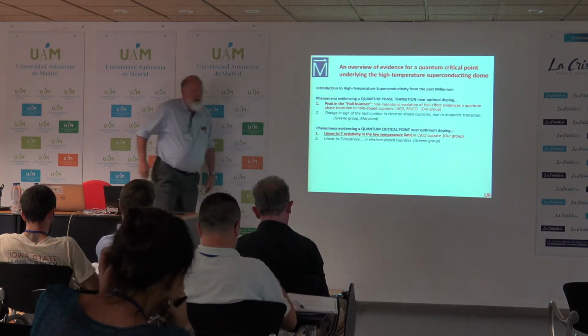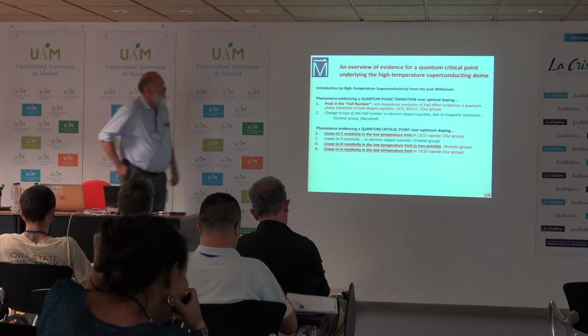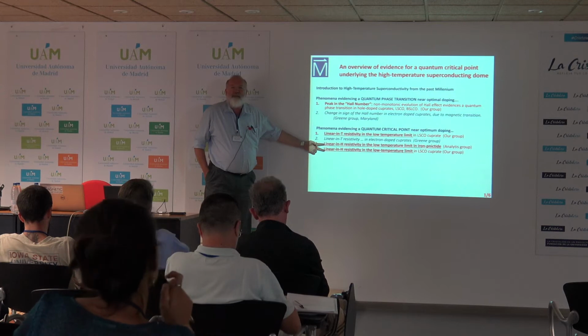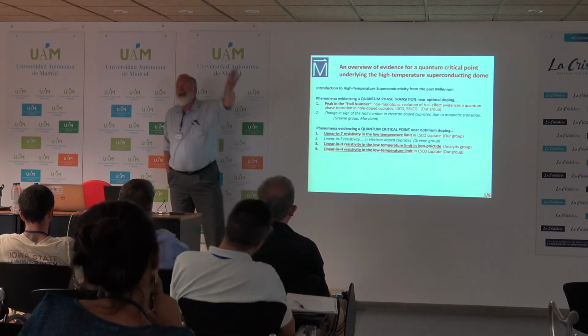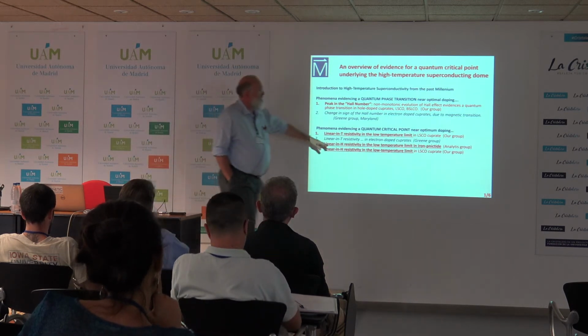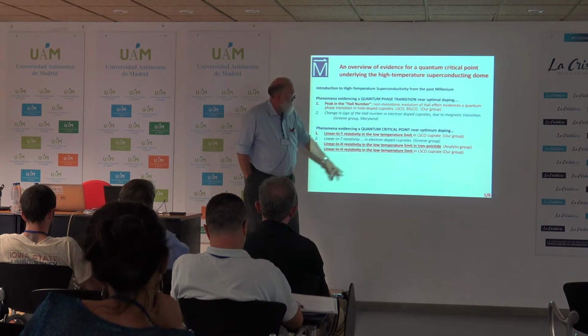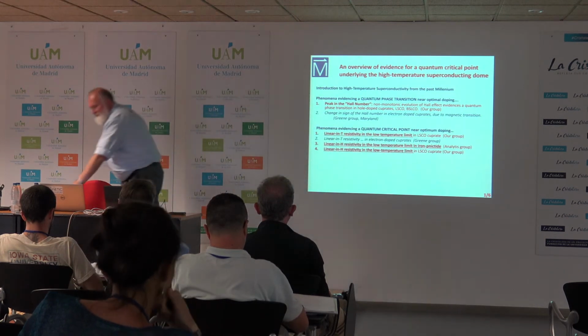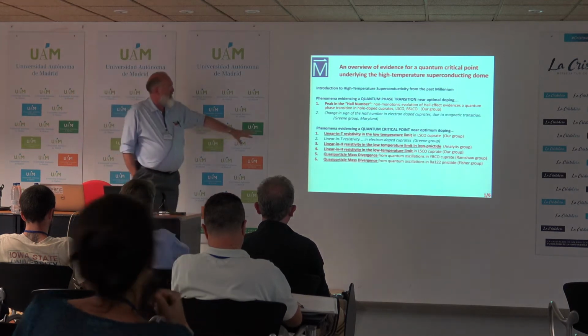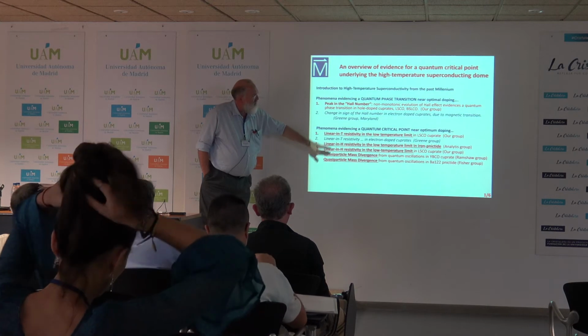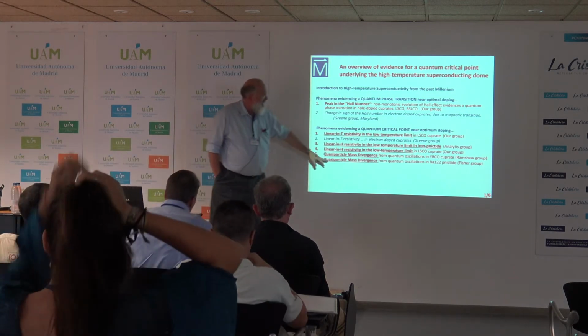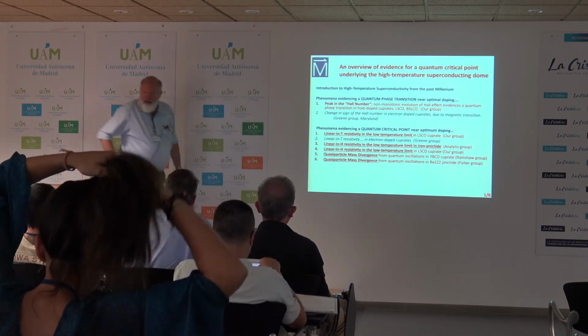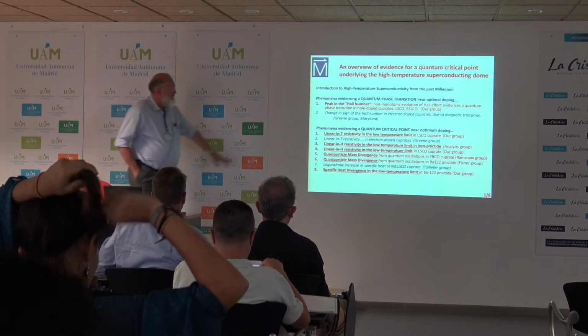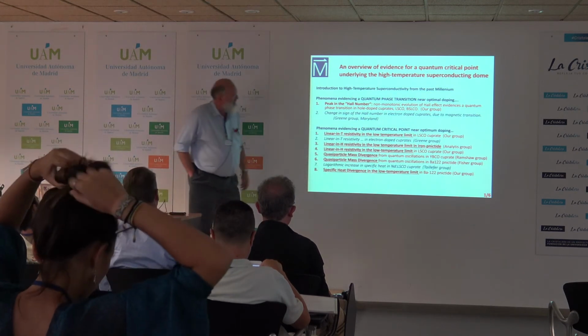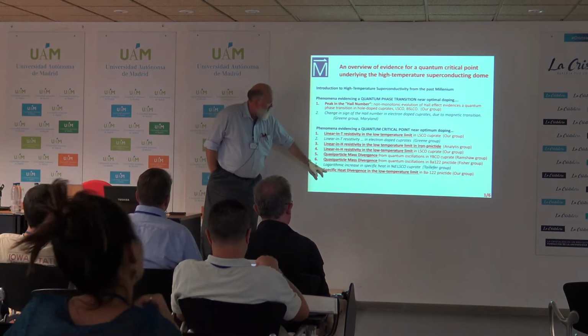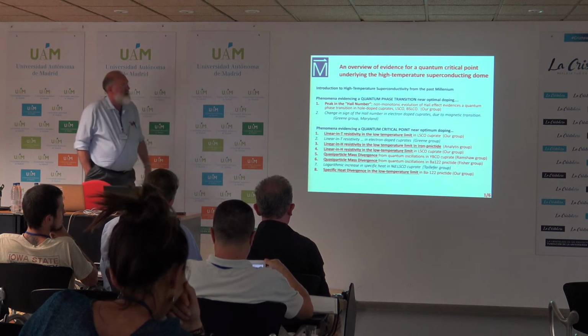I'll mention the linear T resistivity, although that was covered quite well in the previous talk. There's recent reports of linear in magnetic field magnetoresistance. So absence of any scale in magnetic field in the low temperature limit in both the pnictides from James Analytis' group and in LSCO from our group. And then I'll present some evidence of quasi-particle mass divergence from quantum oscillations in cuprates from Brad Ramshaw, from barium-122 pnictide, Ian Fisher's group. And there's other evidence of logarithmic increase in specific heat, neodymium-doped LSCO. And I'll finish the talk on specific heat divergence in the low temperature limit of barium-122.